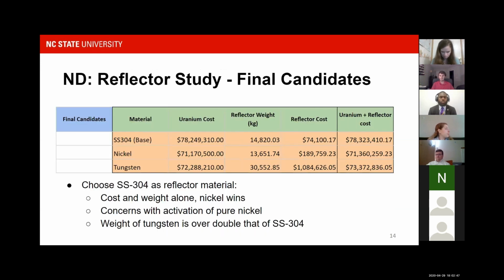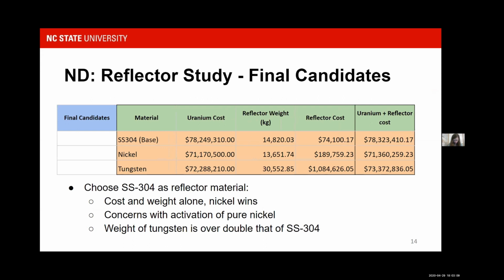For our final candidates, we see that we have SS304 winning out, and this is because though nickel and tungsten have lower overall cost, and nickel has a lower overall weight, SS304 does not activate nearly as much as nickel. We eliminated nickel because of the activation potential, which would complicate recycling or disposal of the reflector, and that would add to the overall cost for decommissioning. And we eliminated tungsten because its weight is almost double that of SS304, so that would complicate the hydraulics needed for our design.